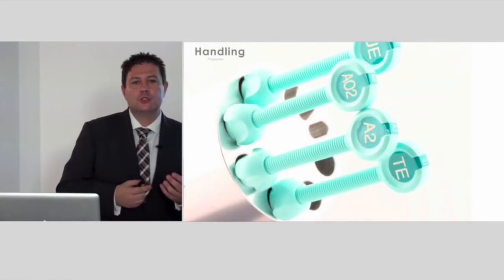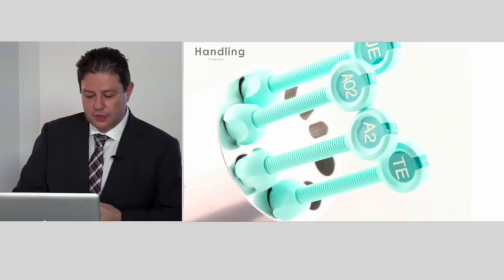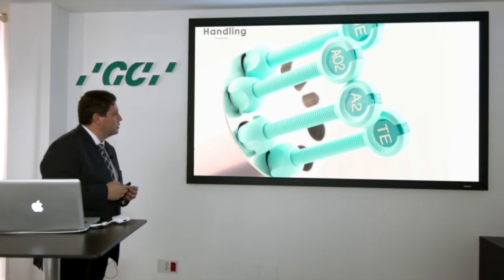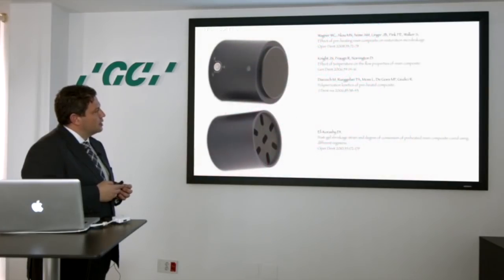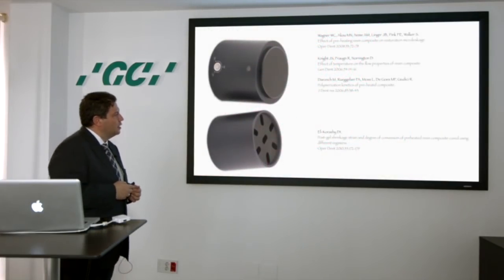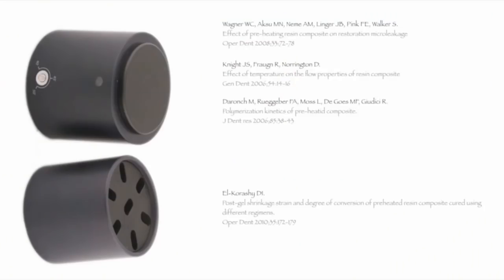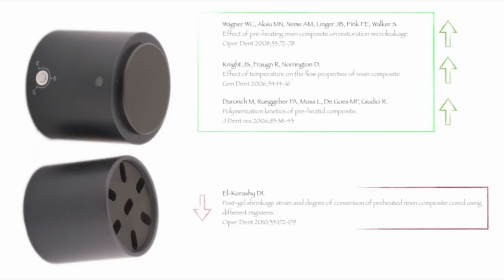The other thing that we do when we use our material is to preheat the composite resins. For this there is literature that says that if you preheat the material, you will have more advantages than if you don't do it. For example, you can reduce viscosity, improve the flowability of the material and decrease the film thickness. On the other hand, the people that say don't preheat the material say that you can increase the polymerization shrinkage. But the fact is that most of these articles are in vitro studies.